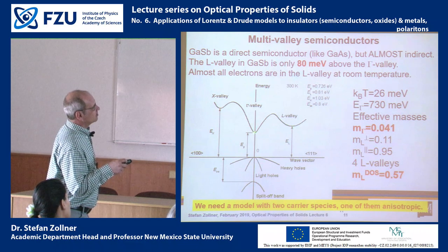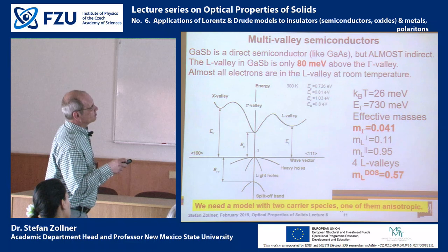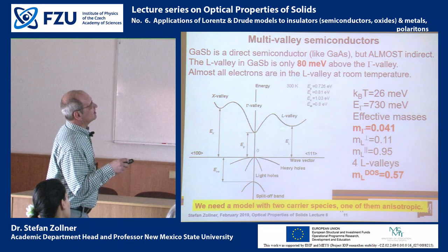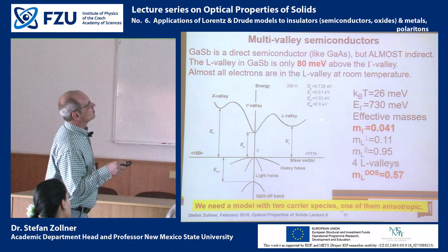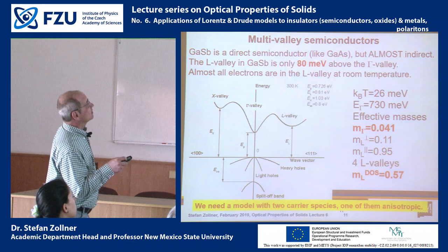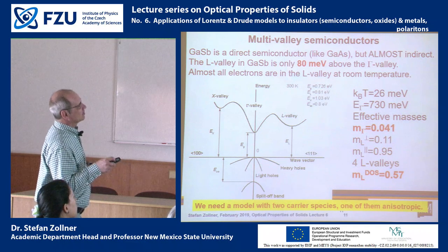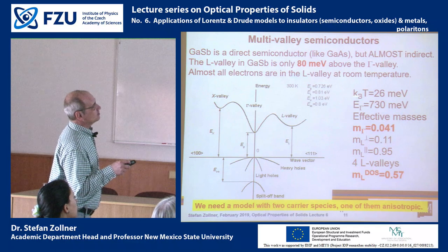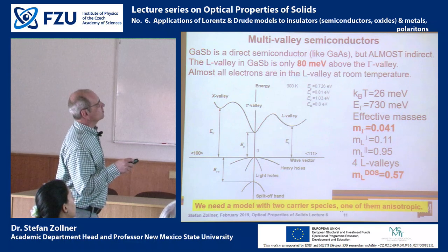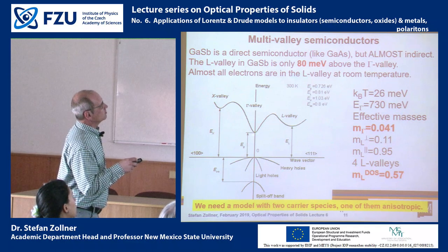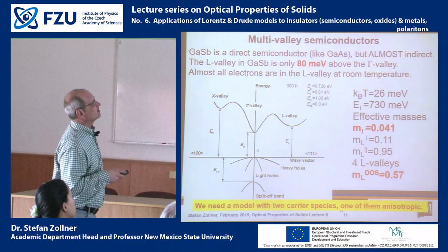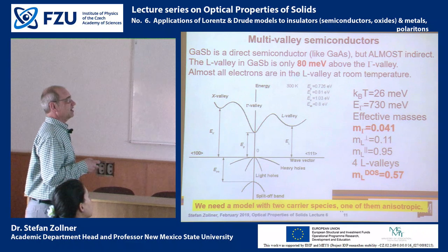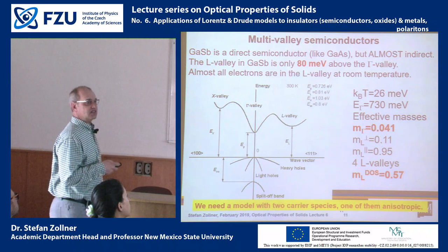And for gallium antimonide, the separation between the gamma valley and the L valley is only, where do I have the number? 80 millielectron volts. So remember, kT at room temperature is 26 millielectron volts. So the separation between the gamma valley and the L valley is only about three times kT.